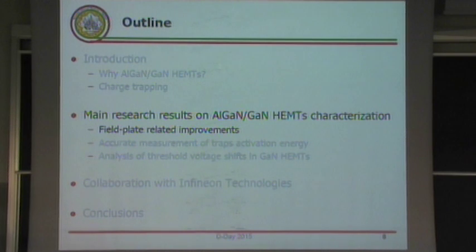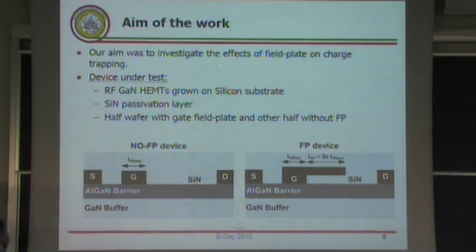So now let's start with the experimental results. I would like to show you this work where we investigated the effect of field plate structure on trapping phenomena. A field plate is a piece of metal that is grown above the silicon nitride passivation. This silicon nitride passivation is an insulating layer grown on top of aluminum gallium nitride to passivate the surface of the device. As you can see here, we have a piece of metal connected to the gate. So in this case, we have a gate-connected field plate, which is extended over the gate-drain access region.